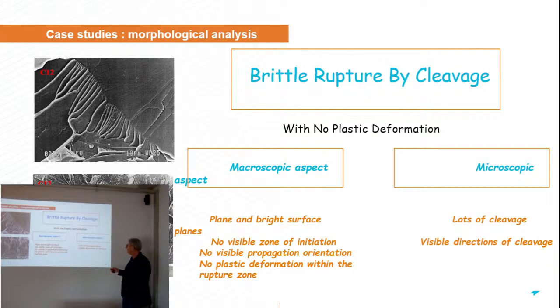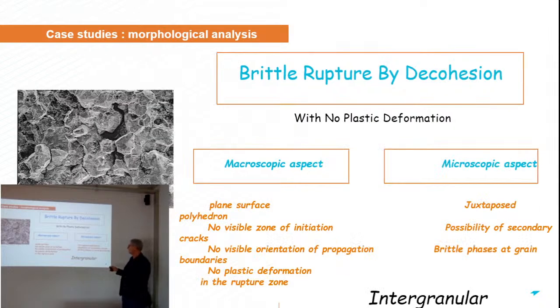So you have no plastic deformation here. This is a brittle fracture. Plain and bright surface, no visible zone of initiation, propagation, no plastic deformation. And when you go to the microscopic scale, you can see lots of cleavage planes. These are given here in the micrograph, and you can see the visible direction of cleavage here, by decohesion, no plastic deformation again, because this is brittle.